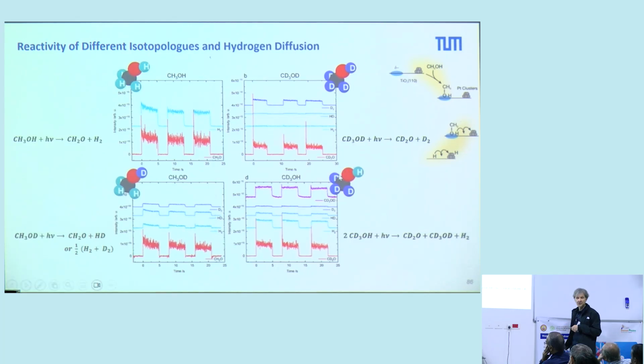On the other hand, if you use this isotopologue, CD3OH, you have another reaction channel going on. You now have an exchange of the OH and you are producing CD3OD. This may indicate that the diffusion of D is lower on the surface. It has time to have this isotopic exchange and produce this isotope.